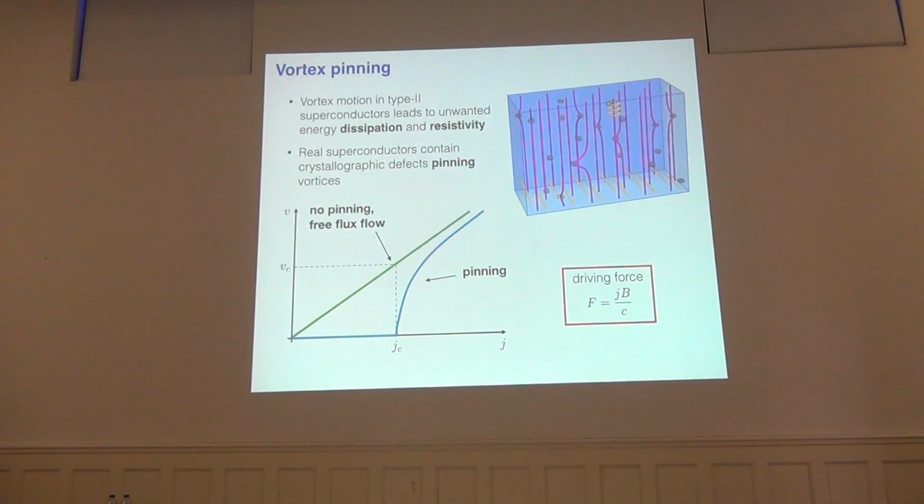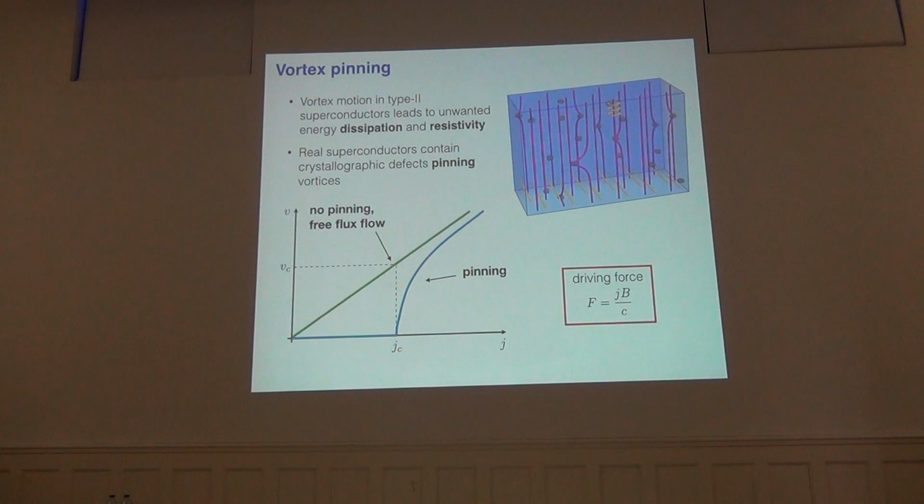So in the beginning, let me flash this beautiful picture of another PhD student, Roland Villa, from our group, which describes vortices inside a superconductor. The vortices are interacting with the defects, and we know that defects are in fact essential to maintain superconductivity, because we want in the end to apply current to the superconductor. Current on this picture is represented by the yellow arrows, and by applying current, it produces Lorentz force on the vortices, and the Lorentz force would induce vortex motion, and at this moment the superconductor of course wouldn't be useful, because the vortex motion would result in energy dissipation and from the experimental point of view in finite voltage, and we would then have finite resistivity.